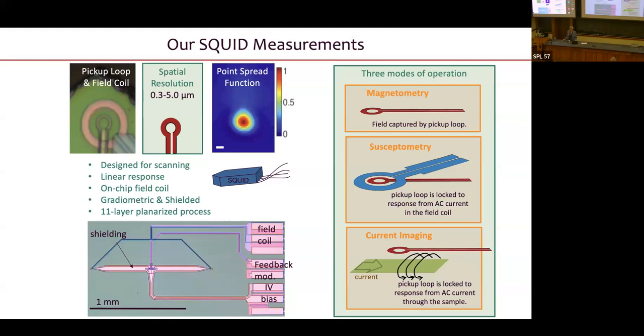But the main point is that we have a superconducting quantum interference device, which is a very sensitive detector of magnetic fields. Don't worry about how it's actually fabricated. This detector has a pickup loop, and we measure the total magnetic flux through the pickup loop, and it has a field coil, so we can apply a local magnetic field by running a current through the field coil. The spatial resolution depends on the size of the pickup loop.